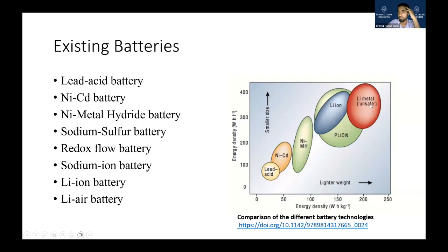It's written unsafe. Why is it written unsafe? The reason is when we are using lithium metal as the anode, there is a risk of dendrite formation. This can give you the highest energy density, but during the charging and discharging process, the lithium dendrite can grow, and it can penetrate through the separator.